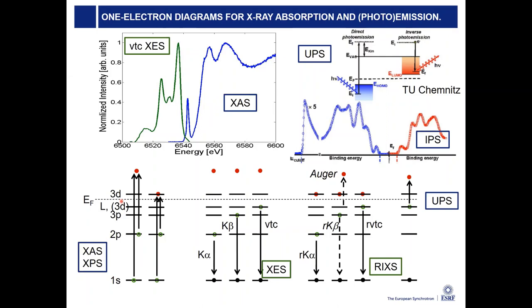So I show here a one electron diagram of various transitions in a 3d transition metal. So this is the Fermi energy. So you have all those levels here populated, and above the Fermi energy they're not populated. If you excite from a 1s or 2p shell, you can excite your electron either to the continuum or you can excite into an unoccupied orbital just above the Fermi energy. So this would be a resonant excitation, that would be a non-resonant excitation. What you can do now, you can measure, for example, the kinetic energy, of course, of your photoelectron, and then you do photoelectron spectroscopy.